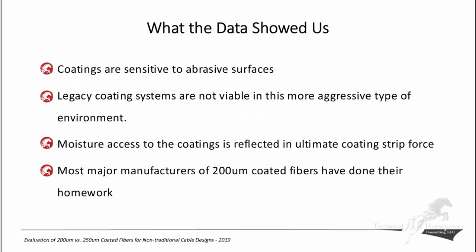So what the data showed us is that our coatings are sensitive to abrasive surfaces above 15 microns, at 25, and most likely at 50. So what that tells me is that legacy coating systems would not be viable, which we sort of expected in this more aggressive environment, which means that we can design cables today we couldn't design 10 years ago.